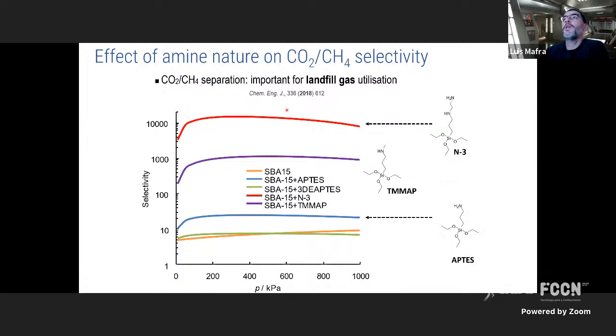So we collaborate with a colleague at the Technical University of Lisbon, IST, Moisés Pinto. He's a professor there, and I've been collaborating with him for several years already, and he is our contact point to perform adsorption studies. So he checks the selectivity when you have mixtures of CO2 and methane, which is a very important mixture to separate for many applications. And to our surprise, we got a factor of 10,000 when you have a diamine like this, which drops to about 1,000 when you have just a secondary amine. And then again, it drops when you have a primary amine.